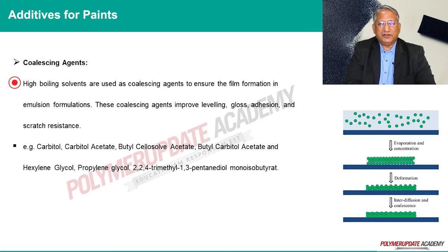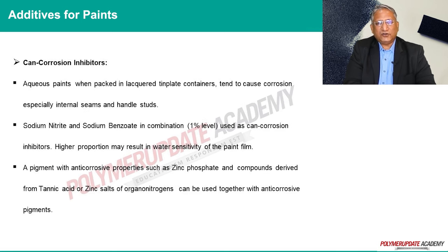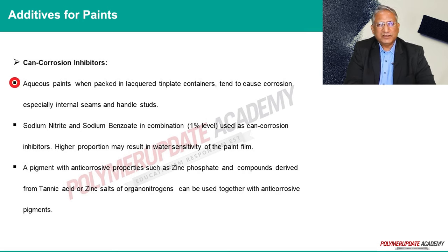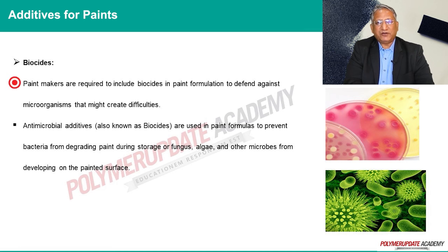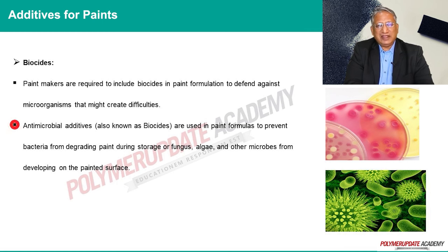Coalescing agents improve leveling, gloss, adhesion, and scratch resistance. Can corrosion inhibitors: aqueous paints when packed in lacquer tin plate containers tend to cause corrosion, especially at internal seams and handle studs. Sodium nitrite and sodium benzoate in combination at the level of one percent can be used as can corrosion inhibitors. Biocides to protect against microorganisms: paint manufacturers must use biocides commercially. Antimicrobial additives, also called biocides, are used in paint formulations to keep bacteria away from spoiling paint during storage and to keep fungi, algae, and other microorganisms from growing on the applied paint film.